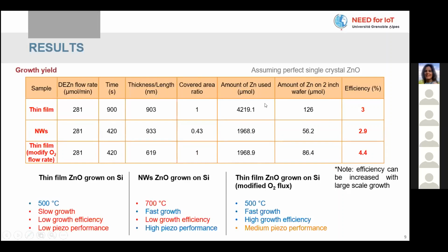So in summary, the thin film that grows at 500 gives us very low growth efficiency and low piezo performance. For the nanowire, we have higher piezo performance, but we have to use a higher temperature, so it uses more energy. But we have faster growth, so we also reduce the time that we use the energy. By modifying the growth condition, we can improve both of them. As you can see, in certain conditions, we can improve the piezo performance and also maintain the economy of the growth process.